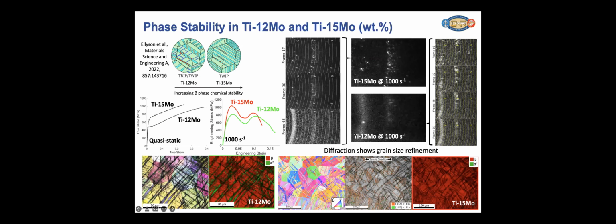Unfortunately, in this case, in the Ti-12 moly, we don't actually see or capture the evidence of the TRIP also happening in the microstructure. But if we go and look at post-mortem microscopy, clearly we see the formation of martensite in the microstructure with deformation. And then our Ti-15 moly clearly undergoes twinning-induced plasticity.